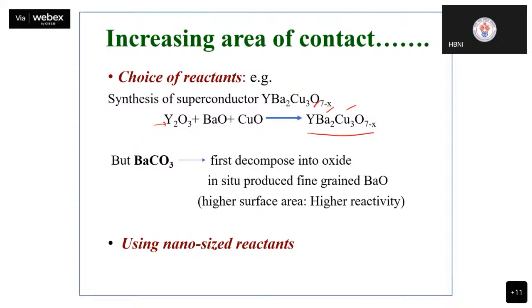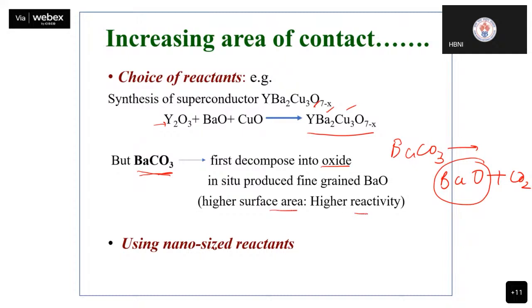But instead of barium oxide, my material scientist instinct tells me to go for barium carbonate. Why? With carbonates, we first give heating at lower temperature, say 600 to 700, depending on the decomposition temperature of your carbonate. So this barium carbonate will in situ decompose first into barium oxide and CO2. This in situ formed barium oxide is very fine grained, so it has high surface area, and because it has just formed, it is highly reactive. Because of this high reactivity, the reaction will now proceed faster, giving you more homogenized products.